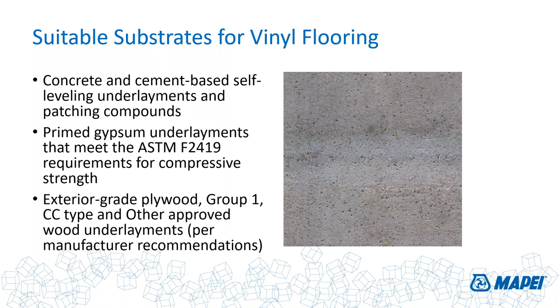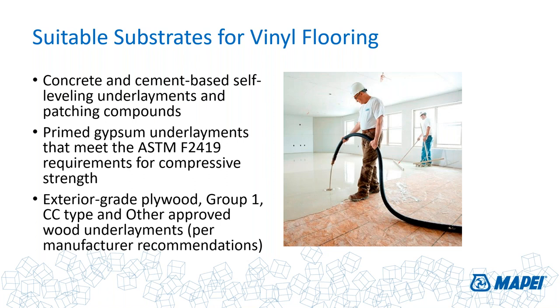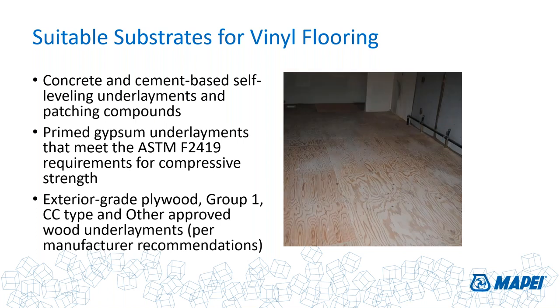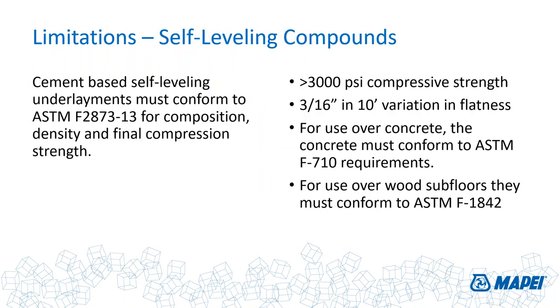There are suitable substrates for this product. Again, concrete and cement-based patching compounds and leveling compounds are suitable. Gypsum underlayments are suitable as long as they meet ASTM F2419. Again, keep in mind that gypsum products do take longer to dry, and you do not want to put an impervious moisture barrier called vinyl flooring on top of that without making sure that gypsum is properly cured. And then you've got plywood materials as well, typically Group 1, CC, marine grade, etc.